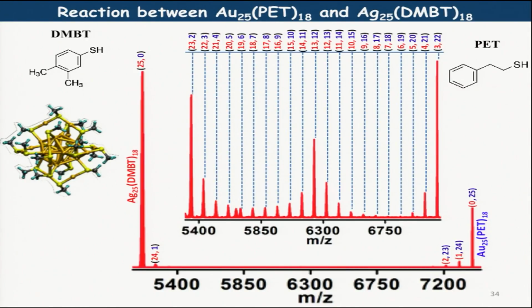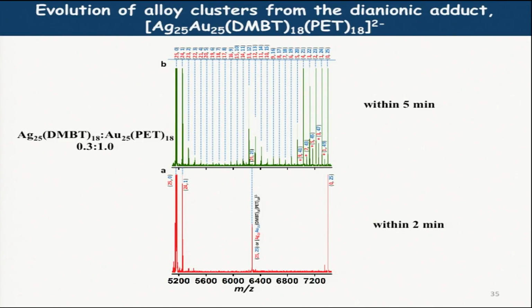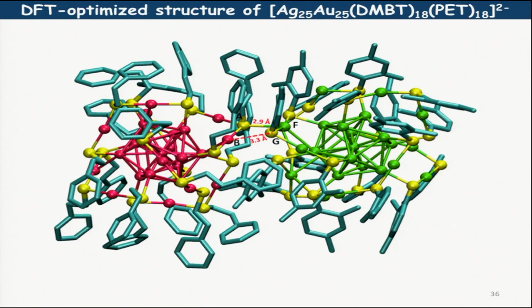And how does it happen? One gold goes from one thing to the other and no change happens in its overall system. This is because these two particles will come together and form a transition state. And they come together and form a species which is just an adduct. And from that, new peaks come up. And I have a lot of details about this, but we have a structure for it.